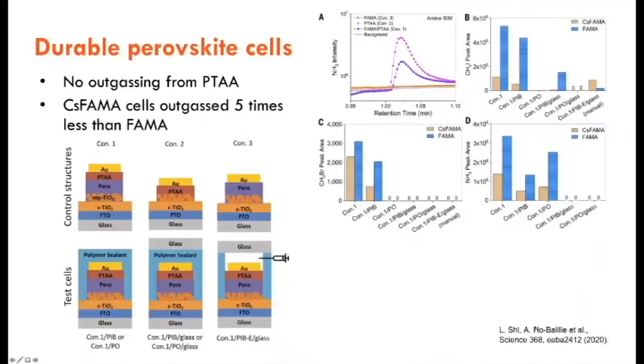So what happens? So then we look at the test cells that are control cells that don't have encapsulation, and we'll also look at the cells with encapsulant only, and then an encapsulant with glass. So typically you'll want a module to have glass on both sides for rigidity, if used for example in solar farms or even solar windows. So this time we look at the cesium FAMA, and as expected, they outgas 5 times less.